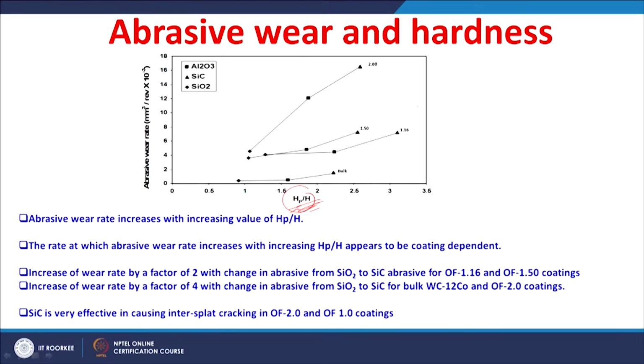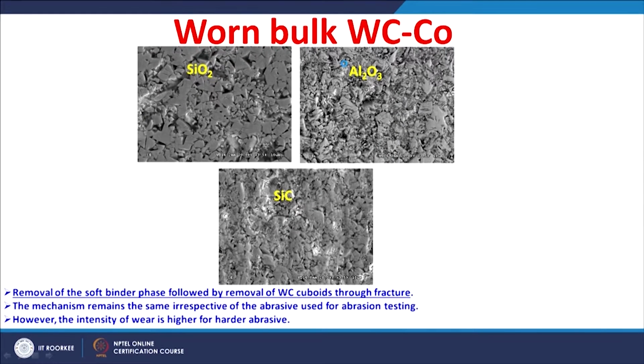The rate at which the abrasive wear rate increases with increasing this ratio appears to be dependent on the coating as well. You can see the increase of the wear rate is almost a factor of 2 with a change in abrasive from silicon oxide to silicon carbide abrasive for those coatings obtained with 1.16 and 1.50 oxygen to fuel ratio, but the coating obtained using a higher oxygen to fuel ratio of 2.0 gave an increased wear rate of almost a factor of 4 with change in abrasive from silicon oxide to silicon carbide. So, we can say that silicon carbide is very effective in causing the cracking and then more abrasive wear. This is particularly observed in the coatings obtained with 2.0 and 1.5 oxygen to fuel ratio.